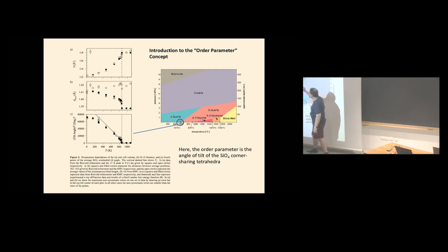And yeah, things change. If we look at the volume, you have linearly decreasing volume, linear expansion, until you hit TC. And then at TC, something crazy happens. You can extrapolate the linear thermal expansion downwards, look at the difference between it and what has formed, normalize that, and then use that as an order parameter. Equally, you could do a similar trick with your silicon oxygen interbond distances.